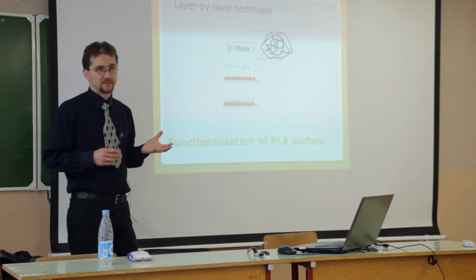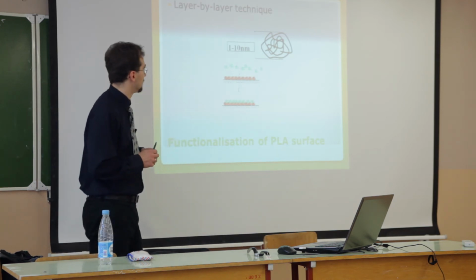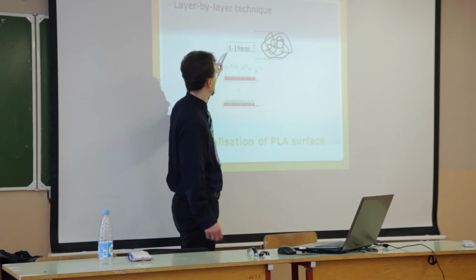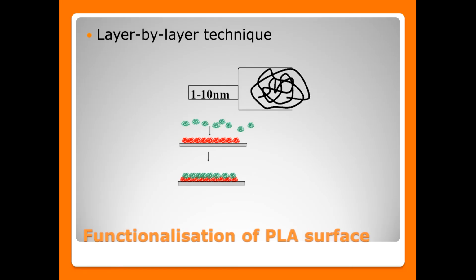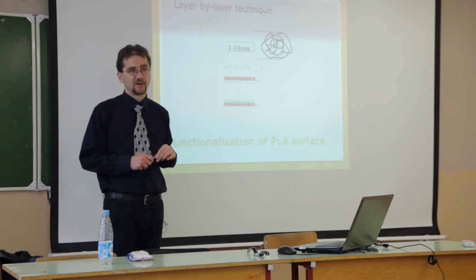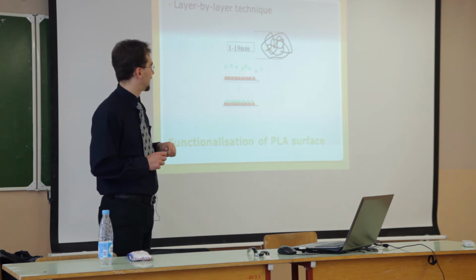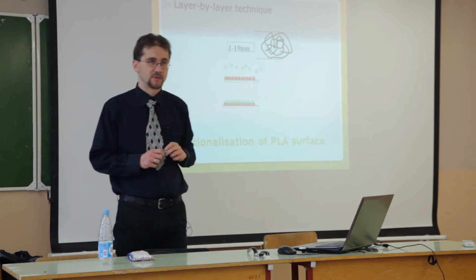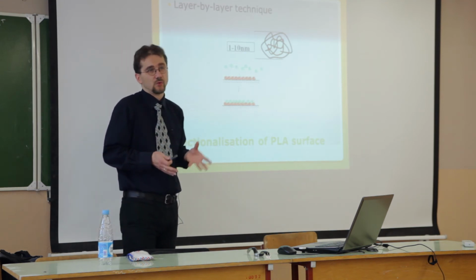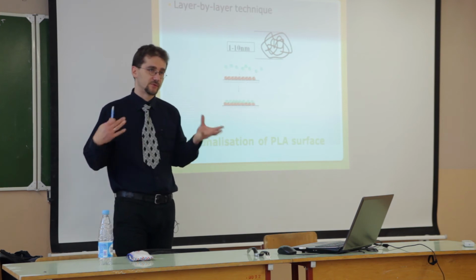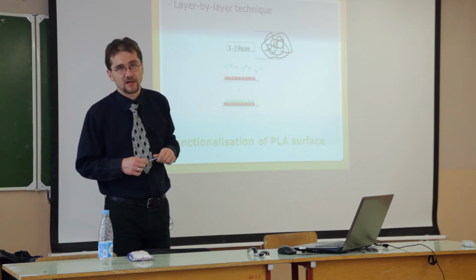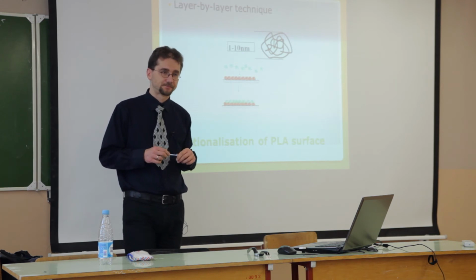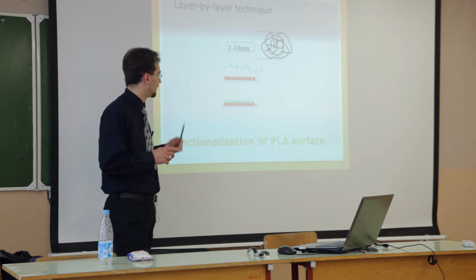We have to know also that it's a kind of nanomodification, because this is a macromolecule, and this macromolecule has a size between 1 and 10 nanometers. So on one side, it is very good to have such thin layers, but on the other hand, it can be not so good, because it is possible probably to use it only for disposable textiles. We cannot wash it, because it is too thin, and the strong mechanical interactions in a washing machine can be too strong for that material.